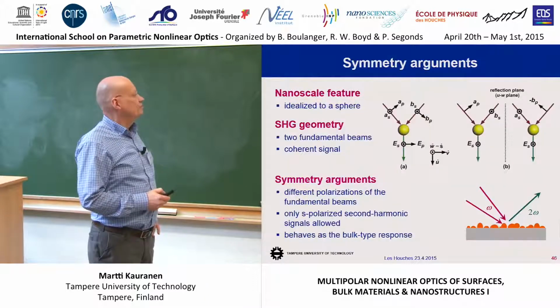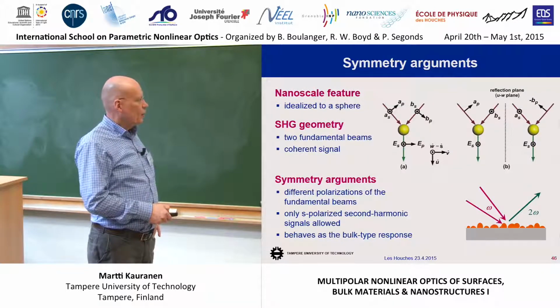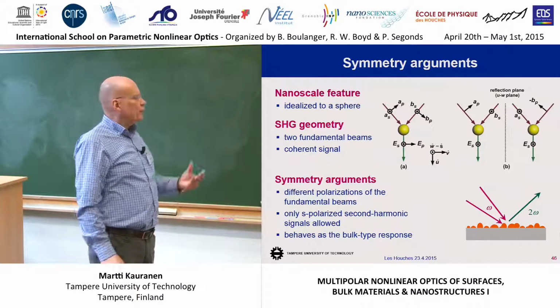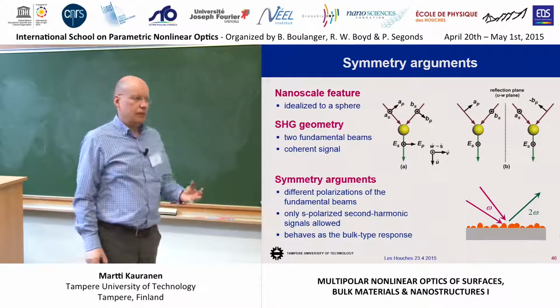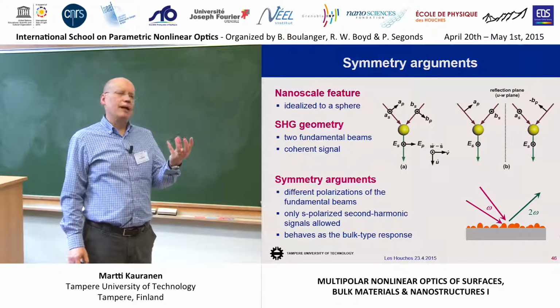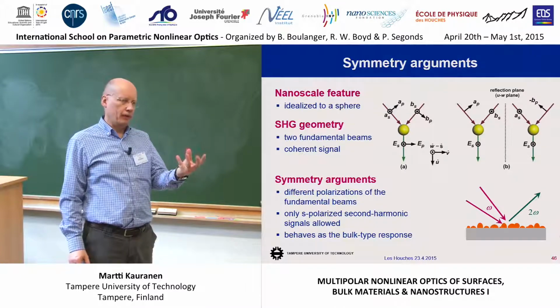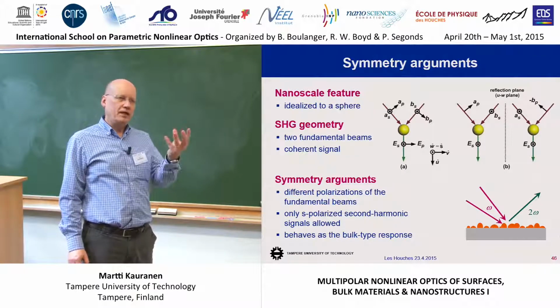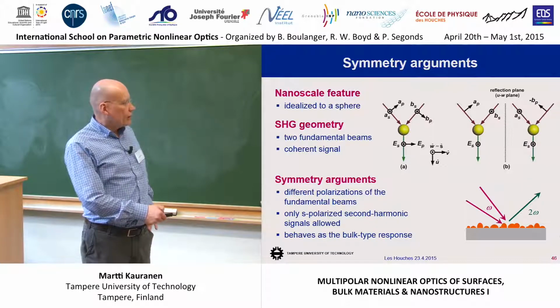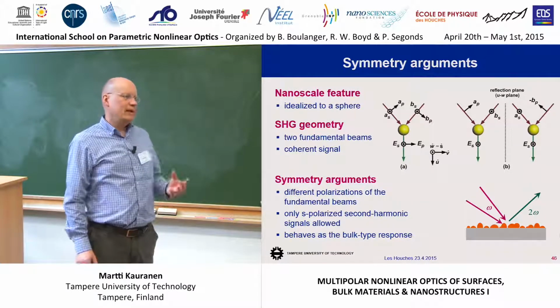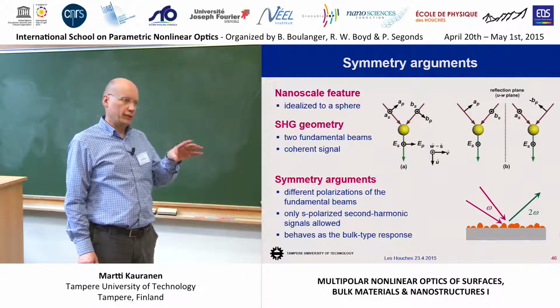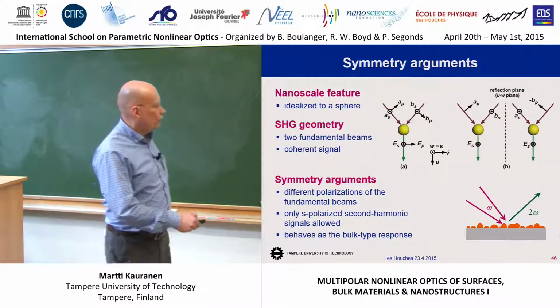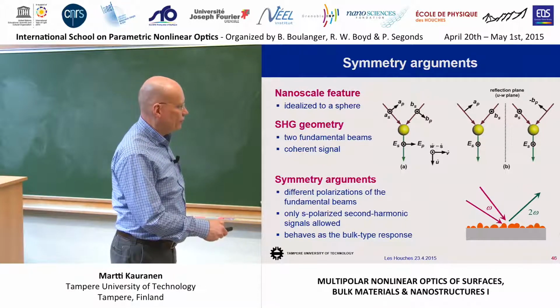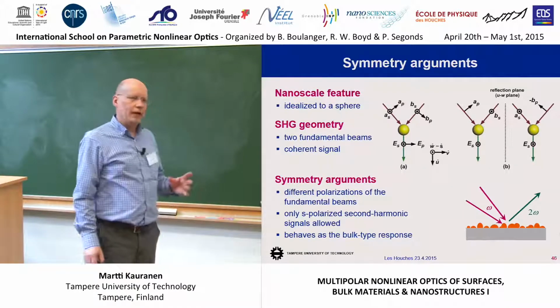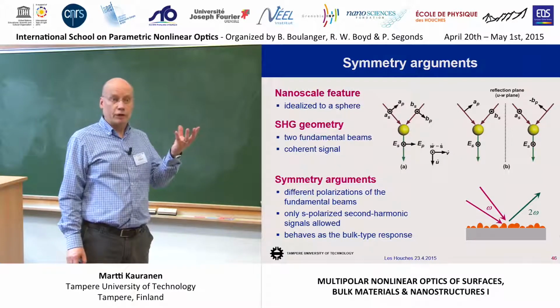This is due to the fact that when you have these nanoscale features, you can interpret that each bump on the surface is a nanoparticle, and you can apply Mie-type scattering theory to that particle. And then when you take into account Mie theory, such a nanoparticle could have, in some sense, an effective higher multipole response, even though at this one location at the interface there's just an electric-dipole tensor. When you integrate over the shape of the particle, you would get, in the effective sense, let's say a quadrupole response. Okay?